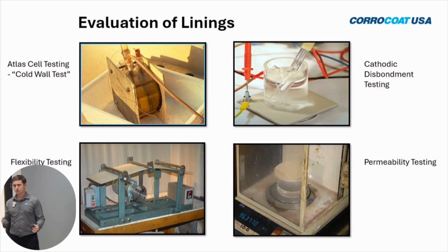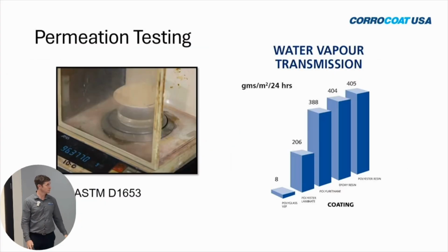So, you know, there's mutually exclusive properties with some coatings, such that if they're highly functional and they have permeation resistance, they may not have as much flexibility and vice versa. You want to find that sweet spot for the given inquiry. And then, of course, permeability testing. So this test uses a free film sample, kind of like this. You put water in here, you have variable pressures and time, and then you monitor how much water is lost. It's a relatively simple test, but it's standard. ASTM D1653, for those of you, if you want to AI it later.